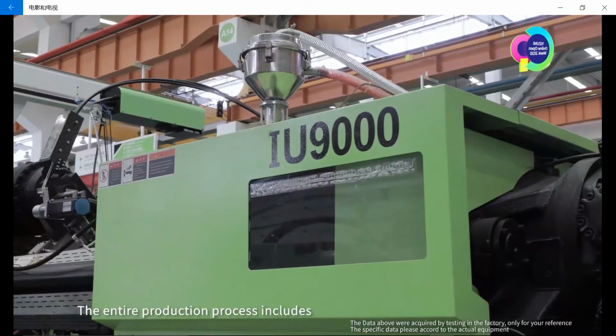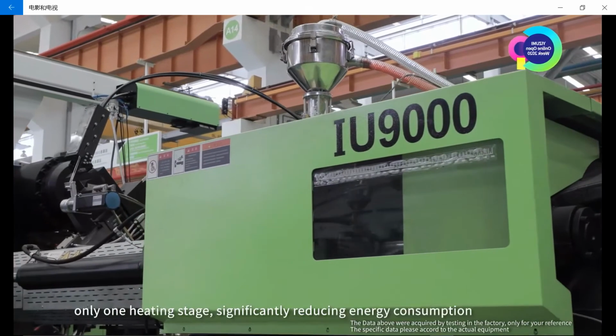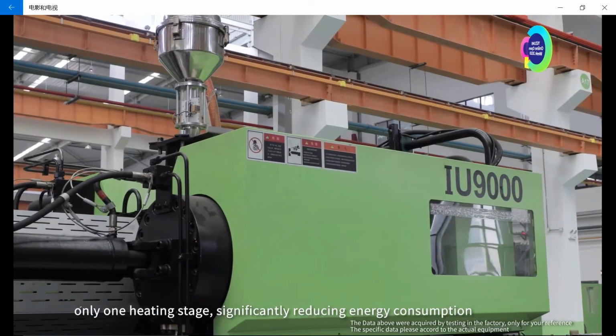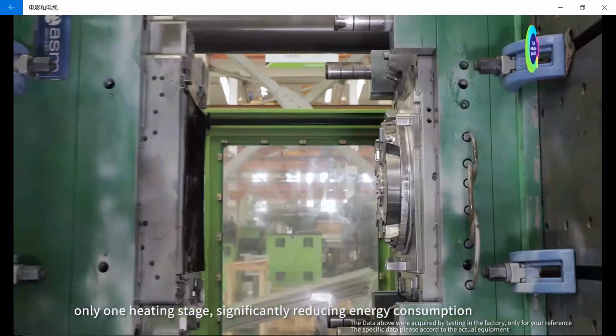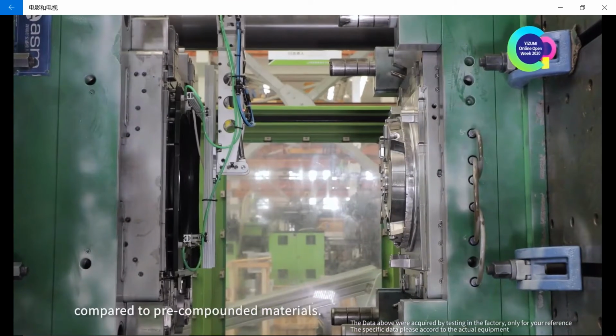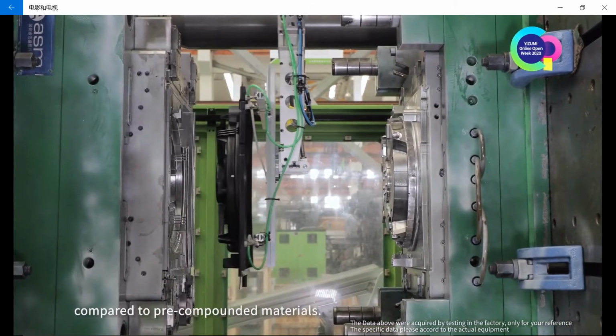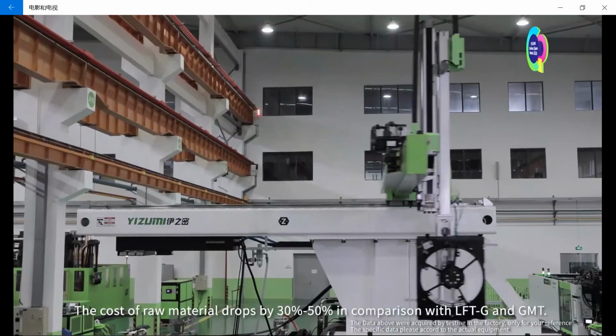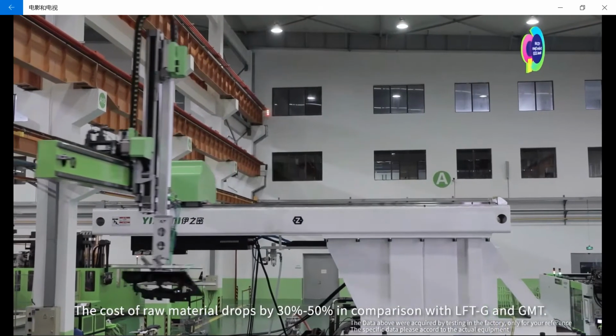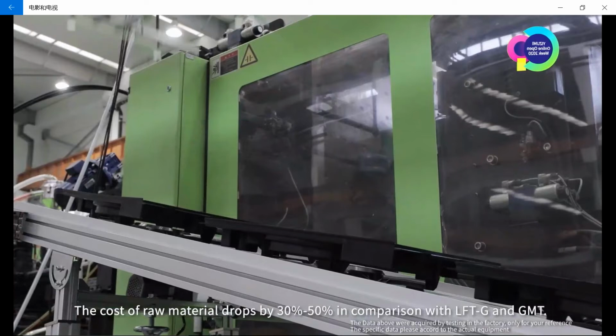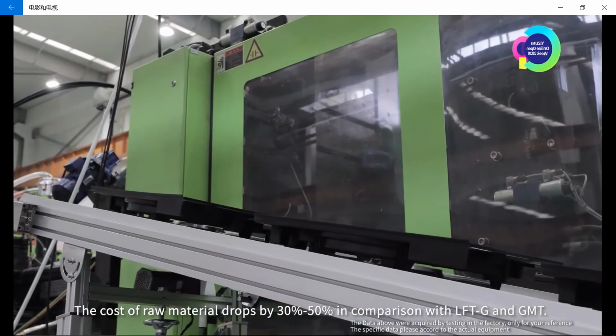The entire production process includes only one heating stage, significantly reducing energy consumption compared to pre-compounding material. The cost of raw material drops by 30 to 50% in comparison with LFTG and GMT.